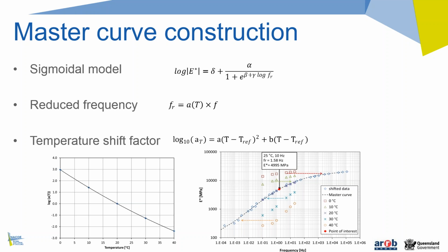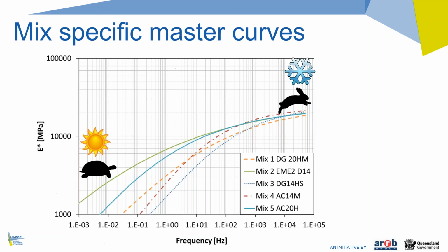Then the shift in the frequency domain is done by using the reduced frequency and changing the frequency in the test to the reduced frequency with the temperature shift factor. The temperature shift factor is again fitted to the data. So the crux to doing the master curve construction is solving the regression parameters in these different equations at the same time, and that can be done in an Excel spreadsheet using the Microsoft Solver function in it, and it's quite straightforward to do that. But I'm not going to go into that at the moment.